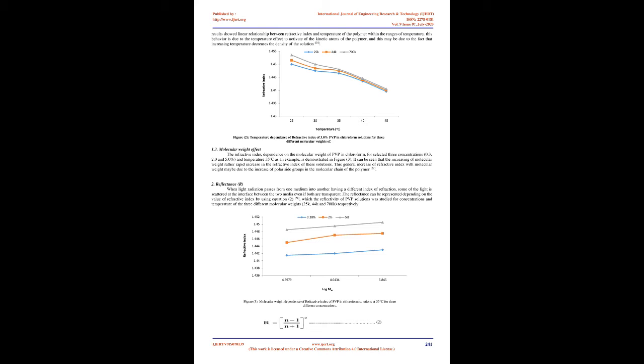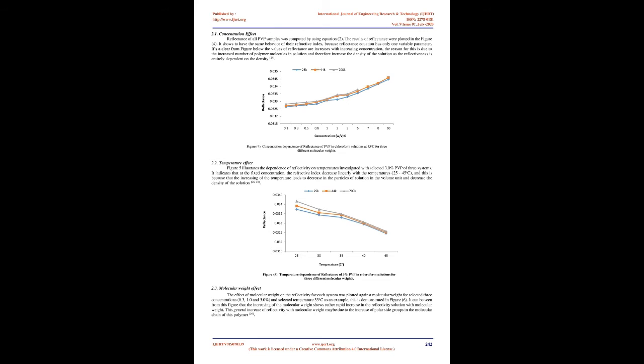2.1 Materials. The 3 molecular weights 25K, 44K, and 700K of PVP were obtained from BDH Limited, England, and were dried under vacuum at 60 degrees Celsius before use. Chloroform was a Riedel-de Haën, Hanover product, monobromonaphthalene. 2.2 Preparation of solutions. PVP 25K, 44K and 700K solutions with different weight per volume percentages, 0.1-10 W/V% for 25K and 44K, and 0.1-5.0 W/V% for 700K, g/ml, have been prepared by dissolving the appropriate weights of PVP 25K, 44K and 700K powder in a fixed volume, 100 ml, of chloroform using a magnetic stirrer for 15 minutes to get homogeneous solutions.